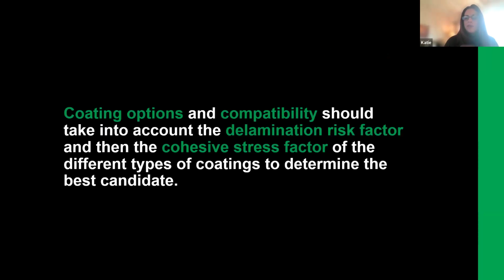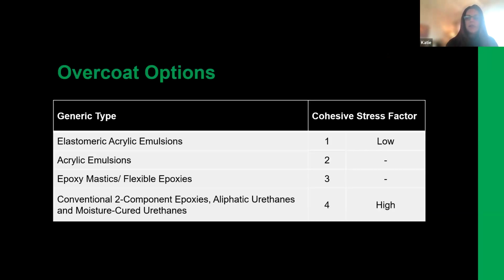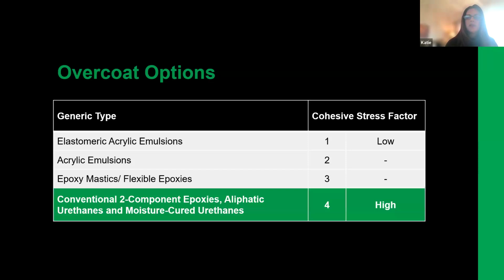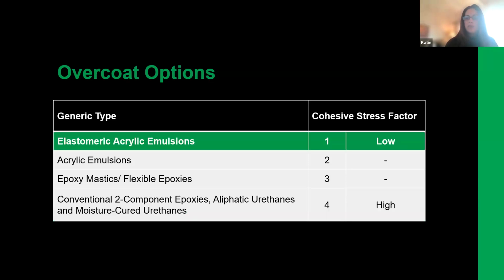So our coating options and compatibility needs to take into account the delamination risk factor and then the cohesive stress factor of the different types of coatings to determine the best candidate. So coating options, compatibility, delamination risk factor, cohesive stress factor, all important things here. The cohesive stress factor, or the cure stresses for our most common coating options, are listed here. So 1 representing lowest cure stress, 4 representing highest cure stress. So you can see our standard 2-part epoxies and urethanes have the highest stress rating for existing coating systems, while the acrylic options are going to have the lowest stress ratings. So pretty easy to see there.